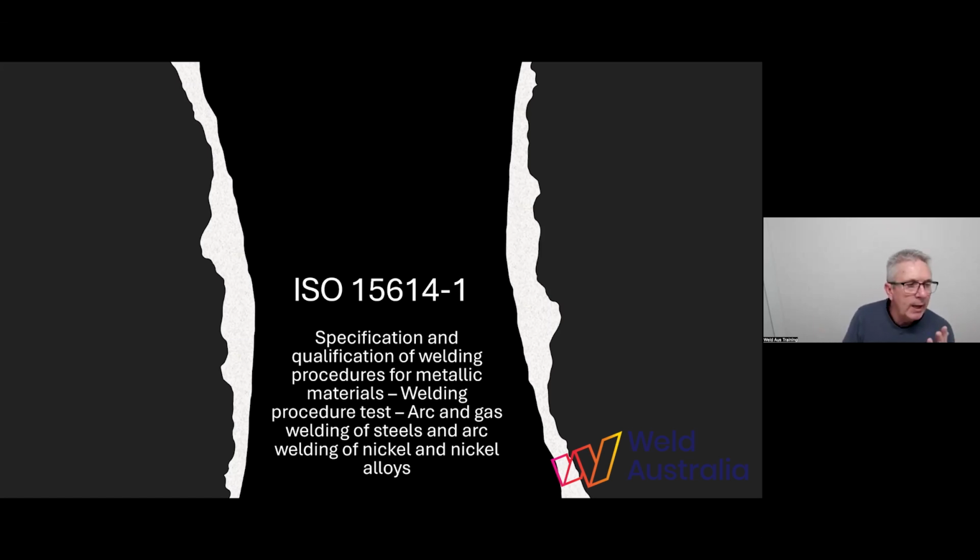When you're looking particularly at our Australian standards, what we've got to consider is the material thickness, the density when it comes to radiographic, and the joint configuration, which will determine whether we can get a good enough image. So sometimes radiographic is not the way we can do it. Let's say we can't do ultrasonic.